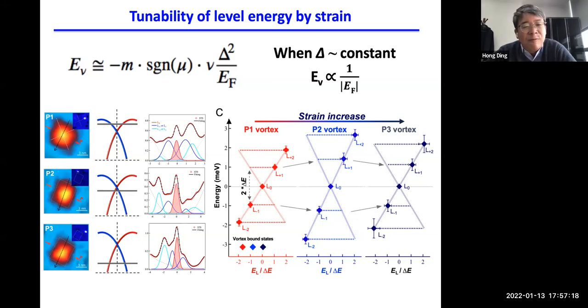In the 1144 case, we see a similar percentage. We see higher, probably 50%, because the surface is a polar surface, so you really have two kinds of surface, which somewhat disrupts it. And in the iron lithium arsenic, we show on the strain that we achieve 75%. In some of the cases, we essentially see 100% in all three vortices, if you apply it on the same. So we think that essentially nails down this problem.